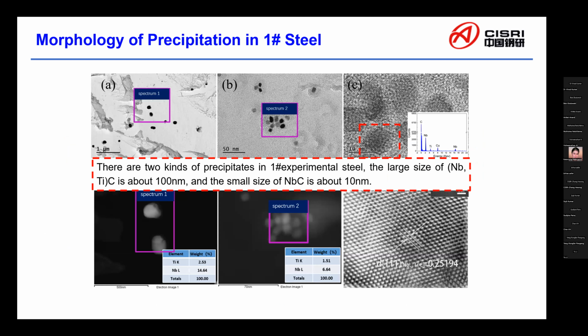Morphology of precipitation is observed in this picture. We can see that there are 2 kinds of precipitates in number 1 steel. The large size of niobium carbide and titanium carbide composite is about 100 nanometer. And the small size of niobium carbide is about 10 nanometer.